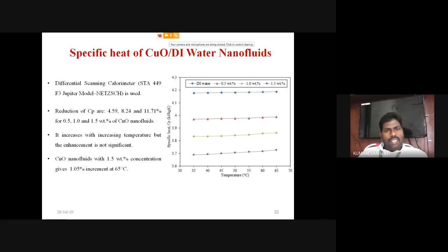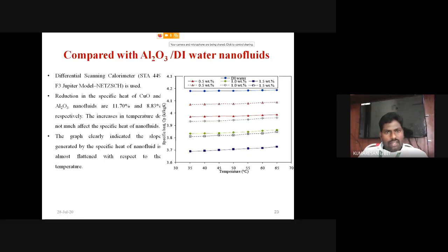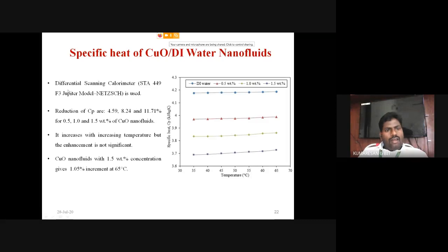The next one is the specific heat of copper oxide and aluminum oxide nanofluids. Then a DSC device is used to measure the specific heat value. Then the reduction of CP for 0.5, 1.0 and 1.5 wt% are 4.59, 8.24 and 11.71% respectively. That specific heat increases with increasing the temperature, but that enhancement is not significant. You see in this graph, that enhancement is almost flat when we are adding the nanoparticles in the base fluid. That enhancement in the specific heat value is almost negligible.